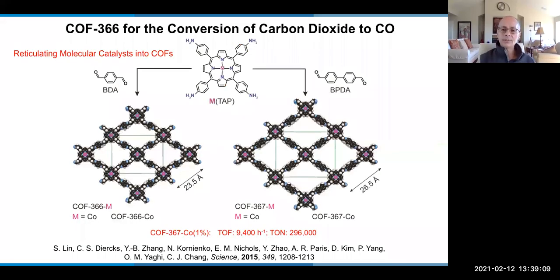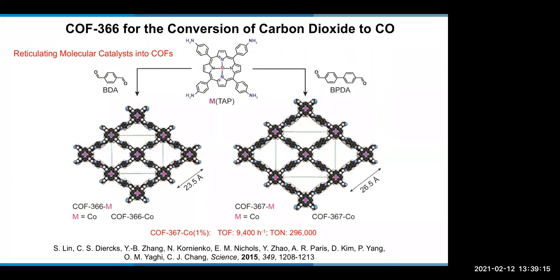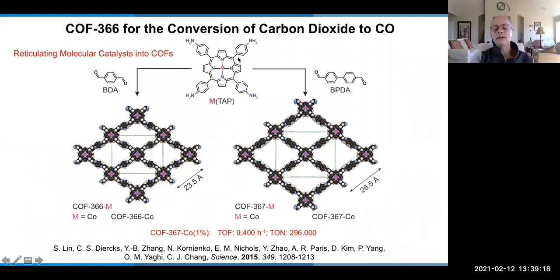Well, another powerful thing about the COFs that we discovered early on is that you can take a catalyst like this, a cobalt molecular catalyst known to convert CO2 to CO. And you can take this catalyst and reticulate it into a COF, meaning to fix it in position and covalently link it into a crystalline network, where the components would be accessible by permeation through the pores. And this was a joint study between my group and Peidong Yang and Chris Chang in our department.